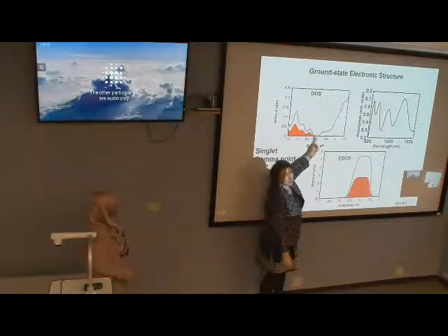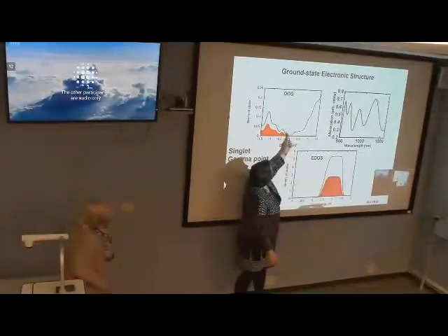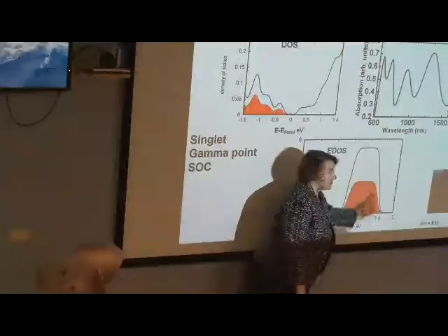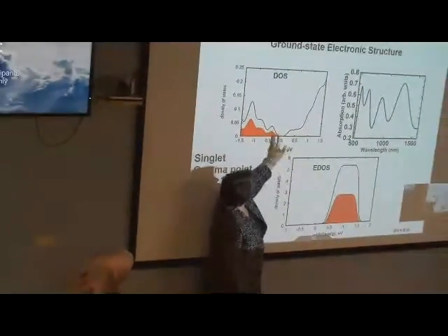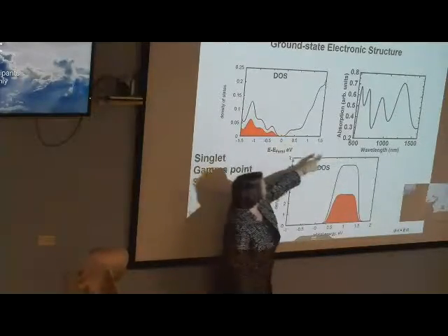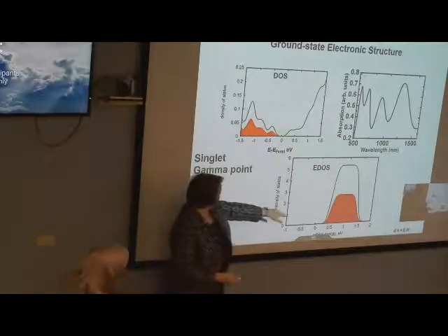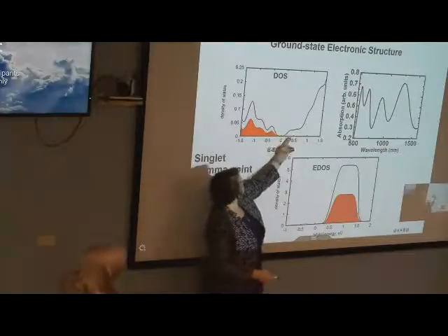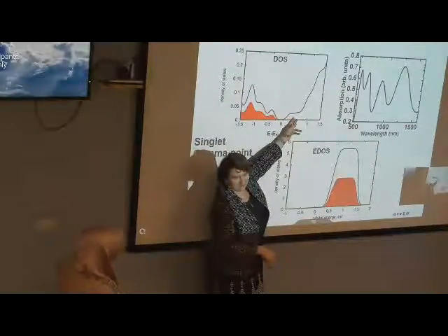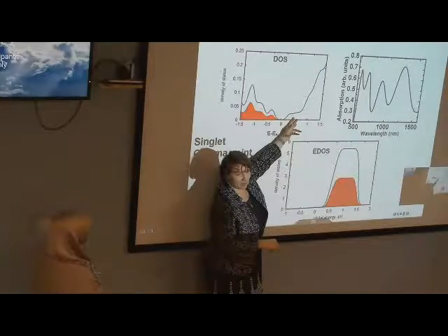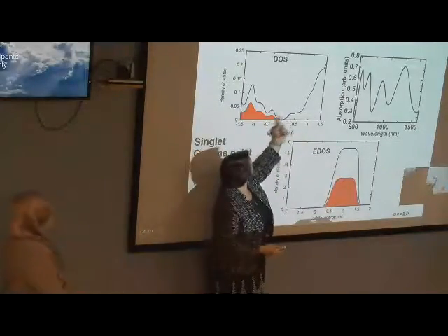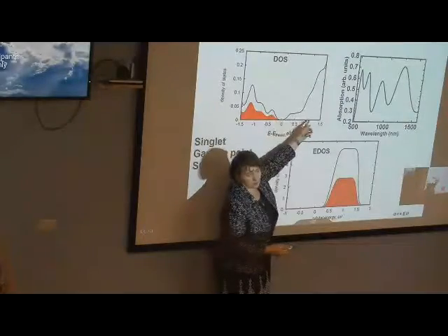If you look at all possible transitions, right? You start with the lowest possible transition, the HOMO-LUMO transition, right? And this is this. Then next. So E stands for transitions, right? But to make them this way, you need to multiply by the oscillator strength, right? And this plot is not really doing it. It's just showing all possible transitions independent of whether they're optically allowed or not, meaning whether they have a transition dipole moment not equal to 0 or they don't. This plot doesn't really show you. It's just showing you all possible transitions from occupied to unoccupied levels. That's it.